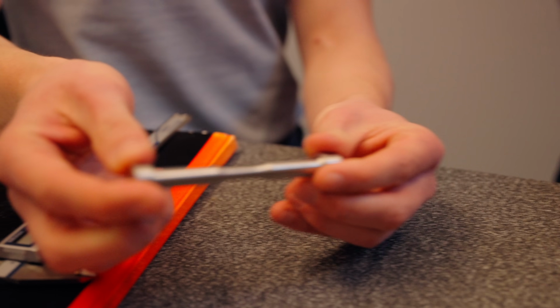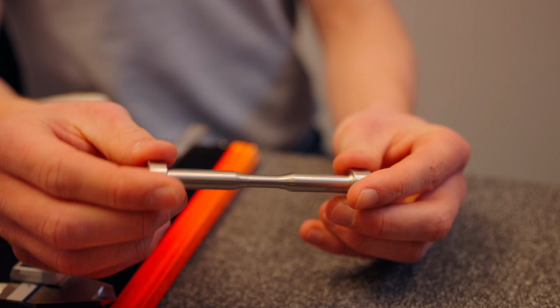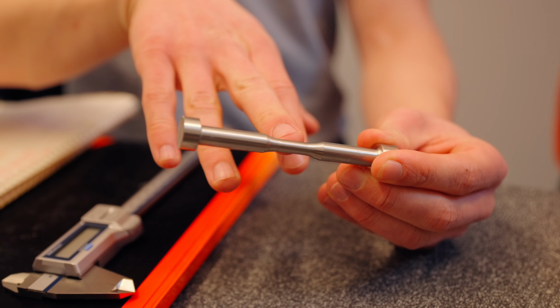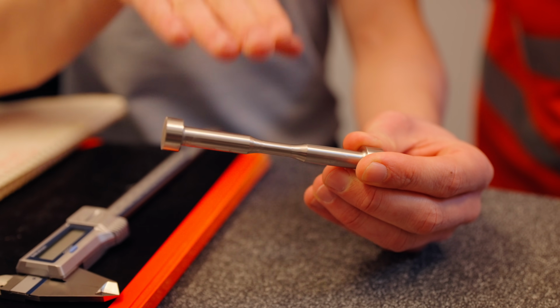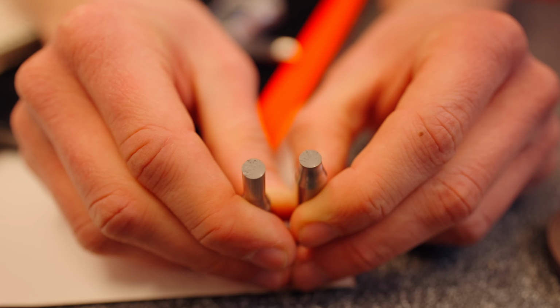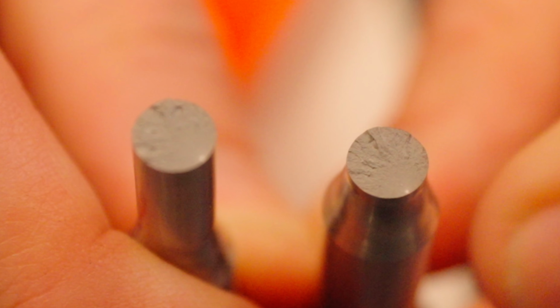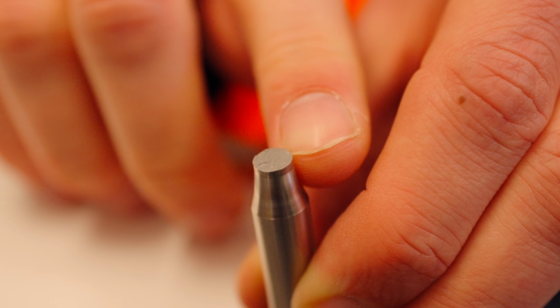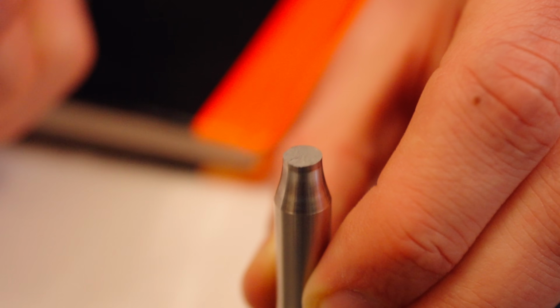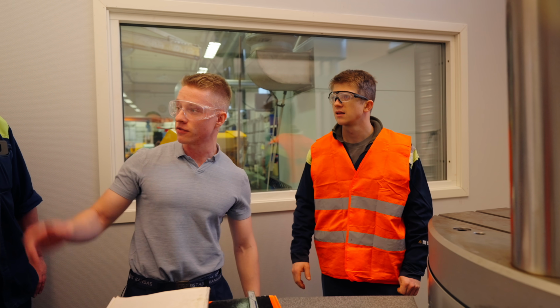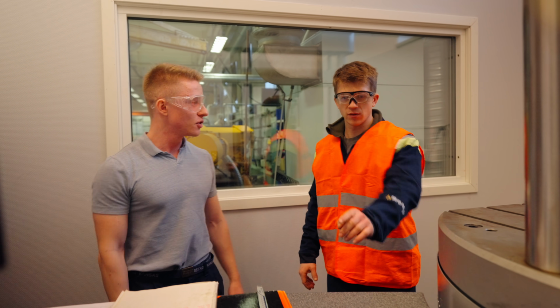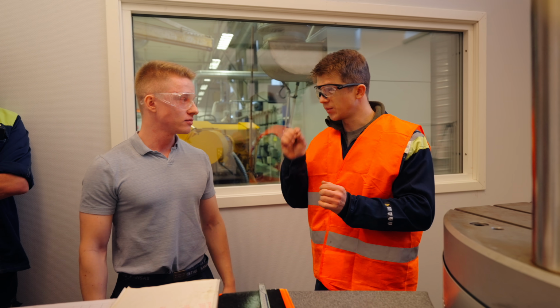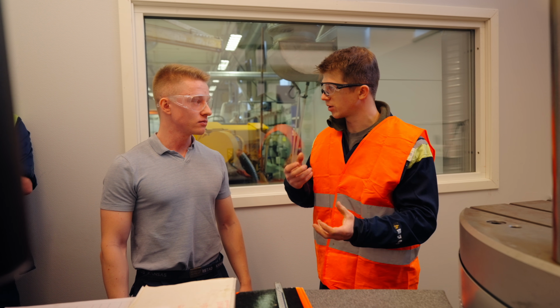So here's one of the dumbbells. So that's machined here on the shop floor? Exactly. That's what you've got that Swiss lathe for? Yes. So we have sort of like a waist right here, and this is where we want it to break specifically. Here we have a broken surface of the material, and you can actually see a white dot. It breaks always at some place, some defect, etc. So this is where it actually starts to break in this fatigue test and just grows out. Okay. And it's also a good way for us actually to find inclusions in the material too. And that little white dot might be, for example, a little tiny inclusion that the crack then propagated from.